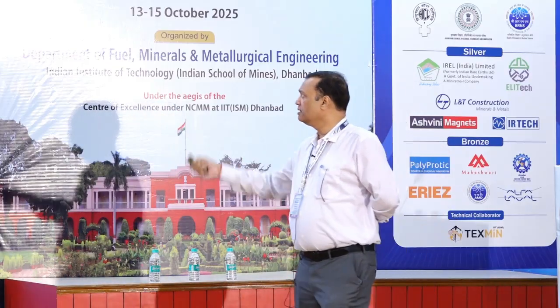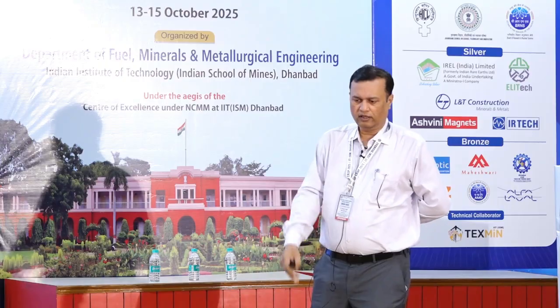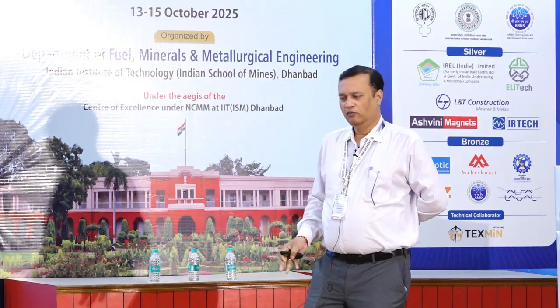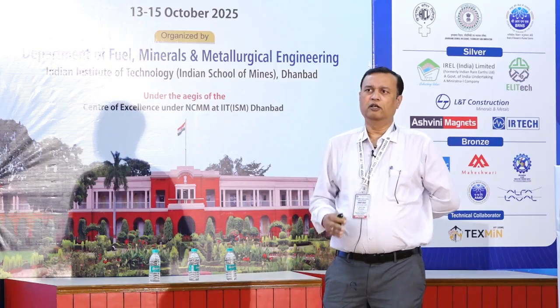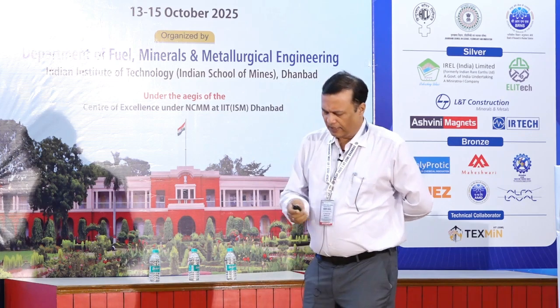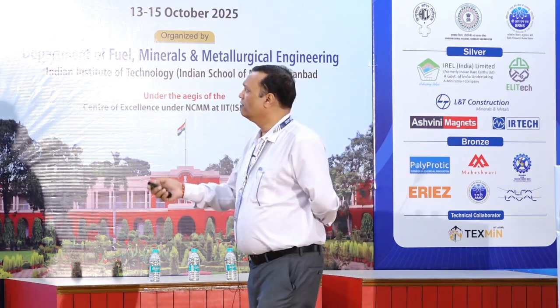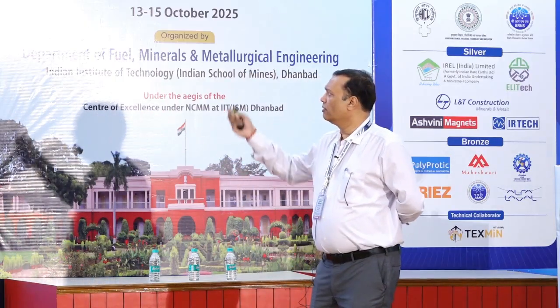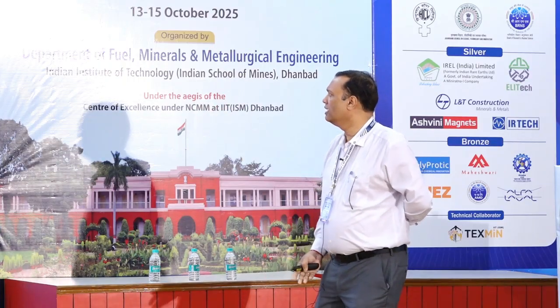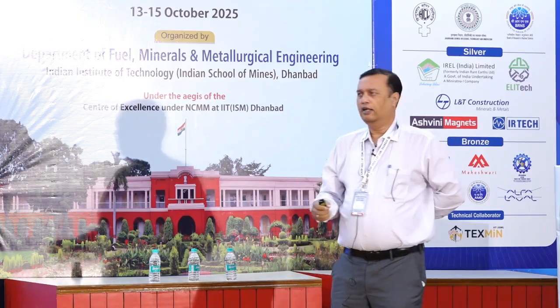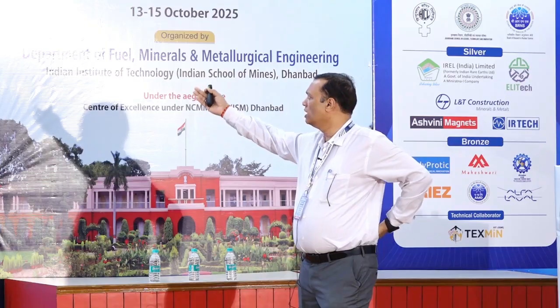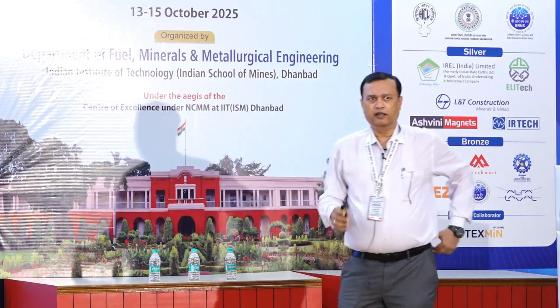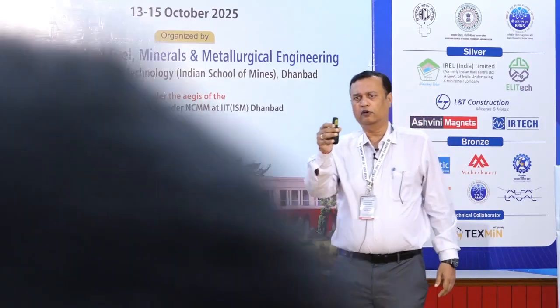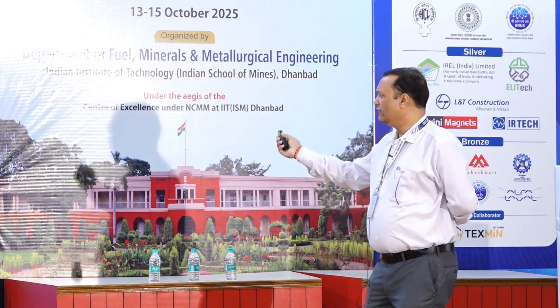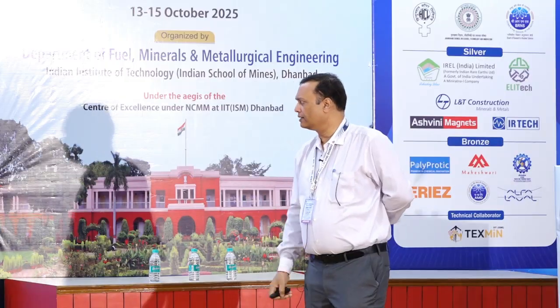So this is the research facility we have at DMRL. This is a very unique research facility that only DMRL has. We are the only lab which can do research in rare earth permanent magnets, produce permanent magnets, and also supply to our defense applications. The rare earth permanent magnet process is a powder metallurgy process where we start from alloy melting, then go for powder preparation, which can be through jet mill or ball mill process. Then we go for orientation of the powder in a magnetic field and do compaction either through a magnetic field press or cold isostatic press to get a green compact. In the green compact, we have particles with one particular orientation that decides the north and south pole of a magnet, and then we do sintering and characterization to get the magnets.